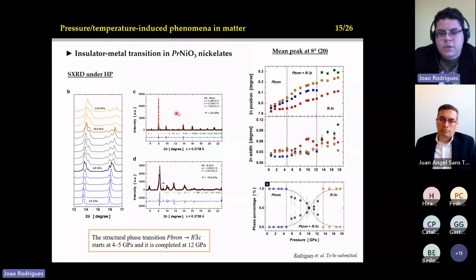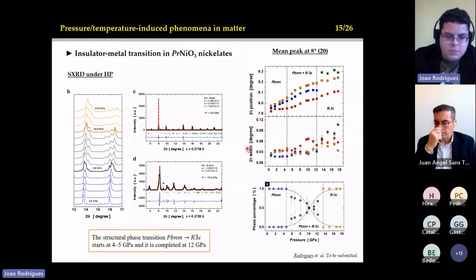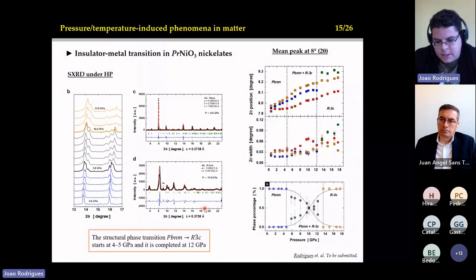And then we started to investigate what is happening under pressure with this material. And then we discovered, using the ID27 beamline at the ESRF, that we have not only a phase transition under pressure from the orthorhombic to the rhombohedral, occurring at 4 or 5 GPa, but we have a coexistence of phases. Okay, we performed this experiment under quasi-hydrostatic conditions, which means that we discard any effect from strain in the sample. And then we managed to also quantify how the quantity of each phase changes in this range of coexistence. So this is a new result.